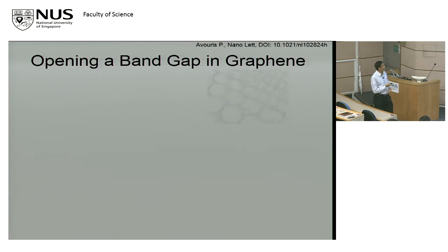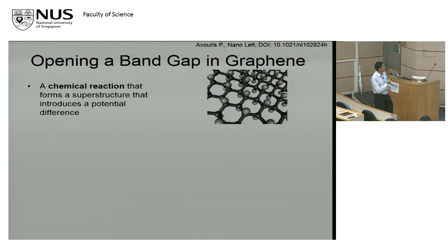So these are some of the general ways you can break that symmetry of the carbon atoms by forming a chemical reaction on the surface. So you either put hydrogen, fluorine, or some other molecule, and then you break the sp2 symmetry. It becomes more sp3-like, and hence it opens up a small band gap. That's one way. But the problem is you compromise the mobility of your carriers on the surface.